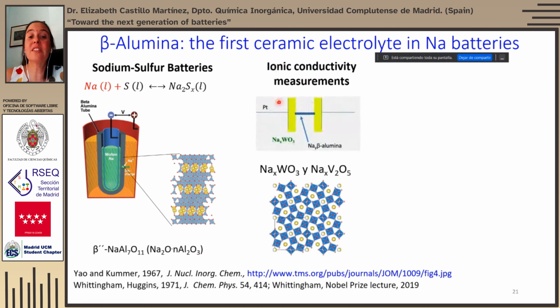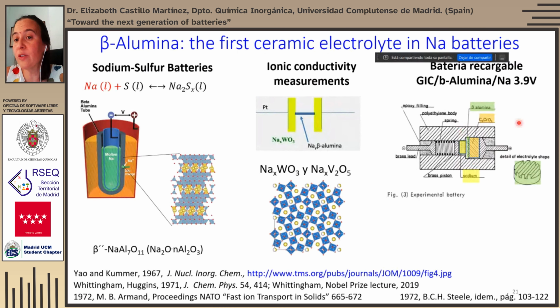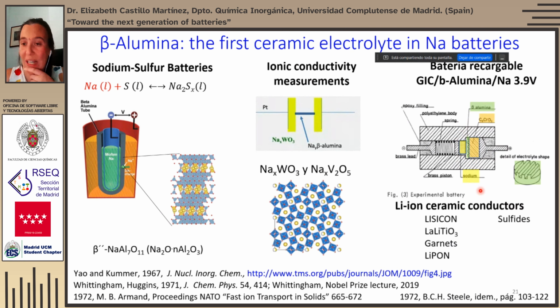Actually, it was in order to study the ionic conductivity of this beta alumina that Professor Whittingham took some insertion electrodes, which could have variable amounts of sodium in their cavities, to do this measurement, and somehow started insertion chemistry. Beta alumina was also used at room temperature by Professor Michel Armand on a sodium battery with graphite intercalation. And since this work from the late 70s, many lithium-ion ceramic conductors have been proposed, based on the LISICON lithium superionic conductor structure, the perovskite lanthanum lithium titanate, as well as the garnets, the amorphous LiPON glasses and sulfides.